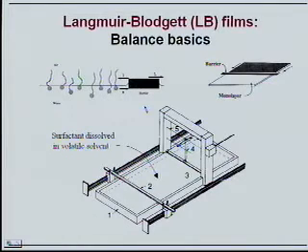So the insoluble surfactant can be compressed by using the Teflon barrier. So you can compress it to a monolayer here, nothing on the other side. Now, the way this works is you have this barrier which moves by two screws parallel to the surface. You have actually a pressure meter, the equivalent of really two-dimensional pressure, which can be just a balance, a small barrier which is equilibrated by a balance.